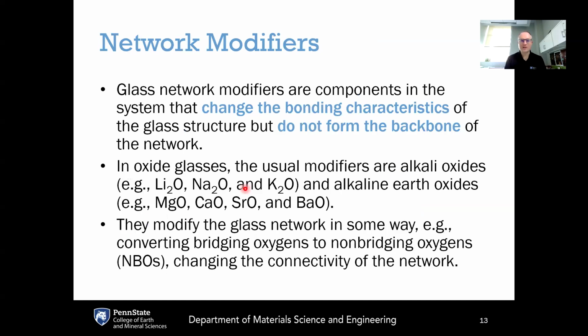Now, the other classification of oxides are what's called network modifiers. Glass network modifiers are the components that are added to the system that change the bonding characteristics of the glass structure, but do not form the backbone of the glass network itself. So for oxide glasses, the usual modifiers are either alkali oxides like lithium oxide, sodium oxide, or potassium oxide, or alkaline earth oxides like magnesium oxide, calcium, strontium, or barium oxide. These alkali oxides or alkaline earth oxides do not satisfy Zachariasen's rules, meaning that they would not be good chemistries to build a random network in 3 dimensions.